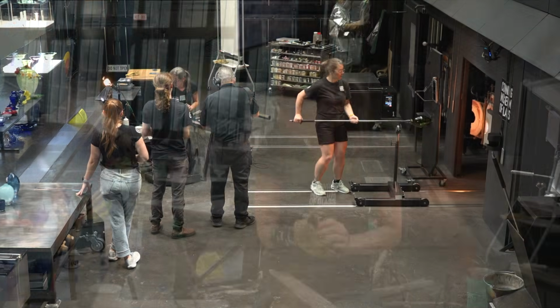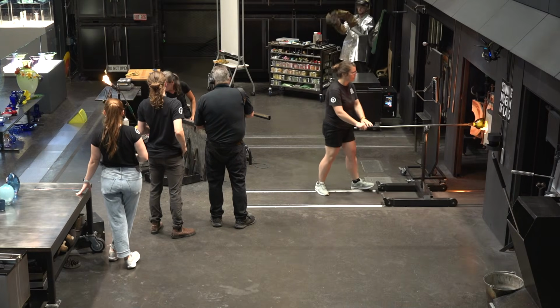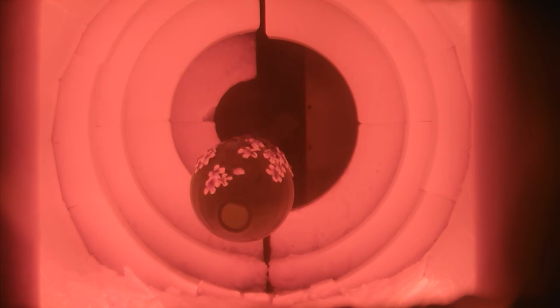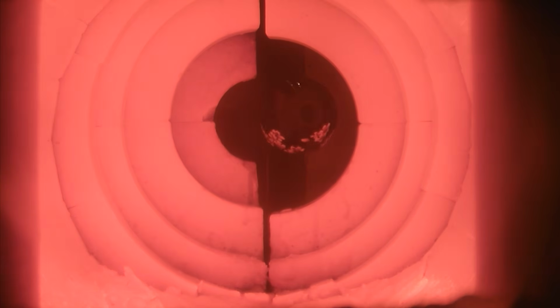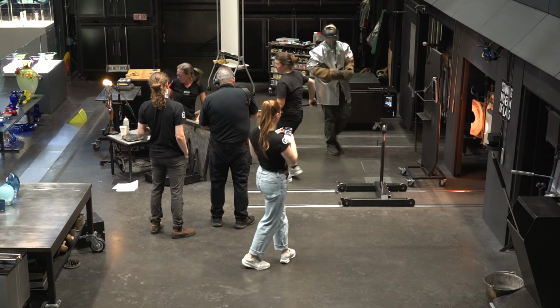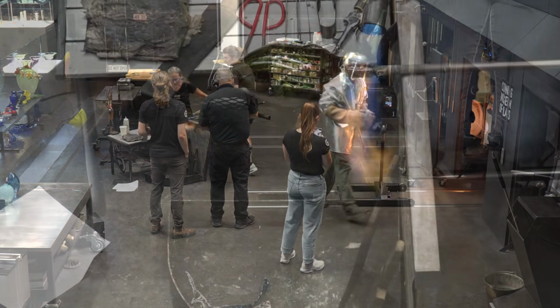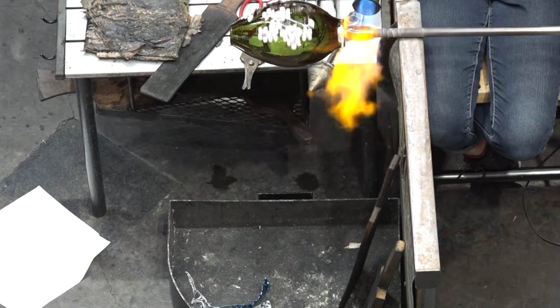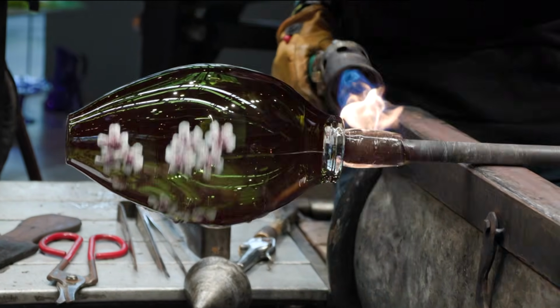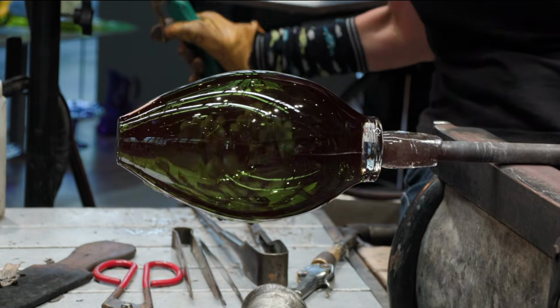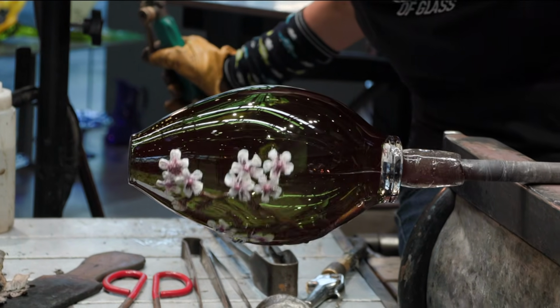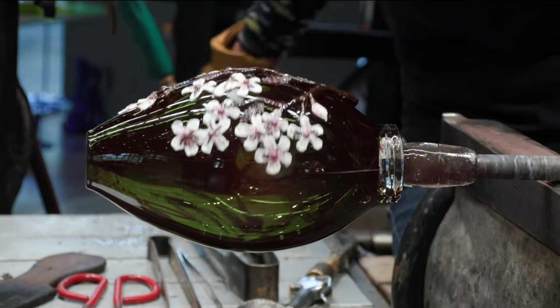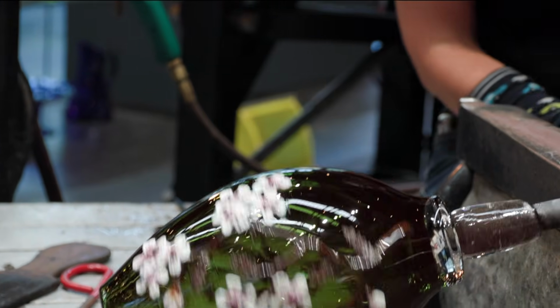How do we know when it's time to return for a flash? We sort of have this internal timer. It's all experience-based. We know what the glass starts to look like when it starts to become cold or when it's been out of the oven. We also know that there is a little bit of timing, and unfortunately the way we know is because we stayed out of the oven for 1 or 2 seconds too long. When in the oven, the whole thing cracked and broke in the oven. Or it cracked out here in the room temperature for staying out too long.